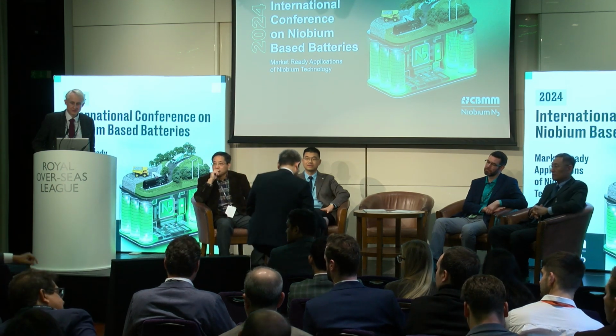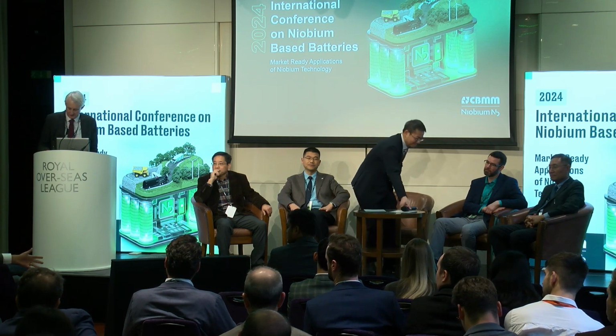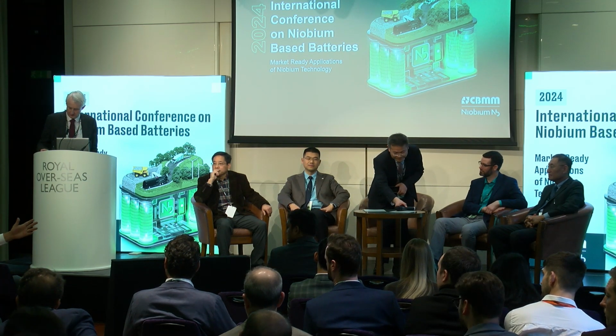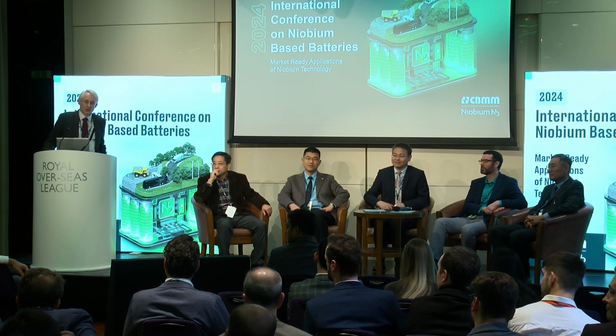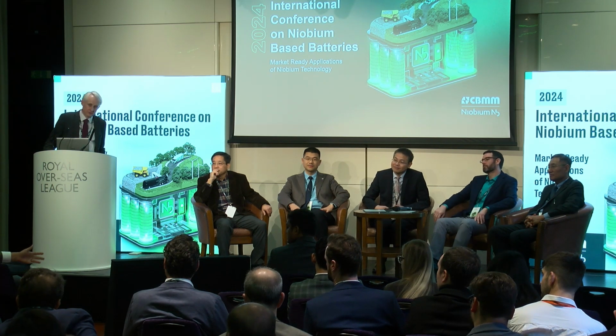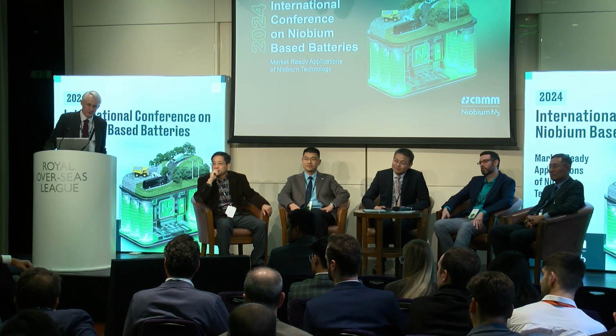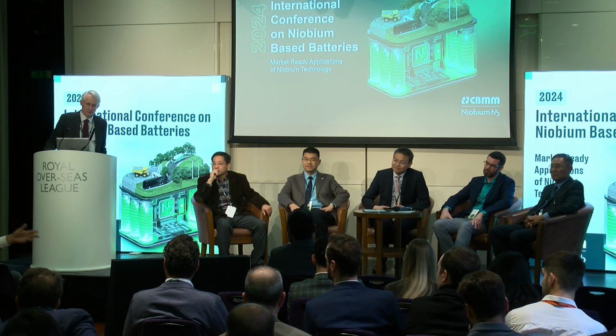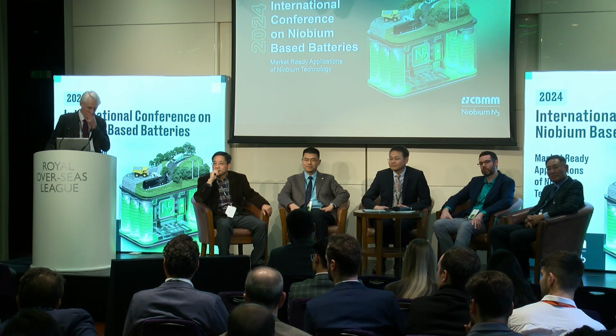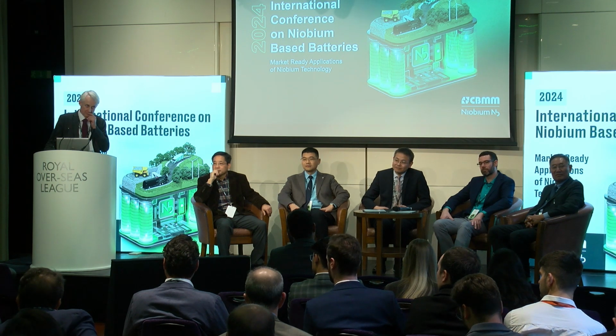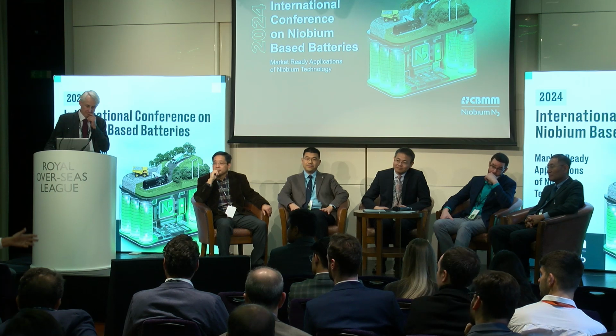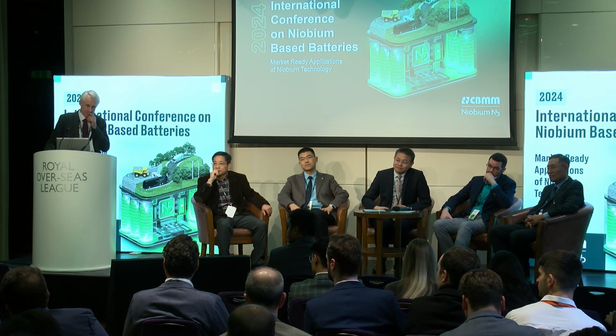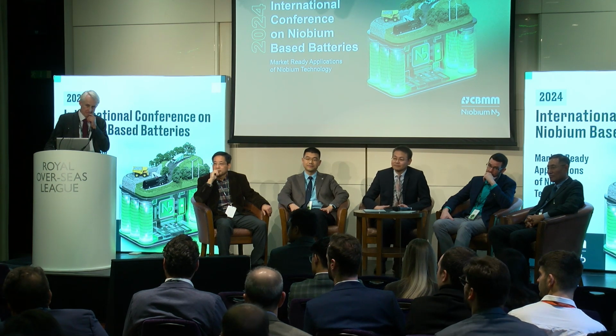No, and in terms of processing or industrial capability so far, and then maybe they can also provide comments. Niobium as an additive is pretty much a drop-in solution. So you do not need any special process capabilities to use and to apply niobium. Of course, you may need to change some process conditions in terms of maybe temperature, washing steps, and how you incorporate, but there is no special need to have any special equipment. It's pretty much a drop-in solution.